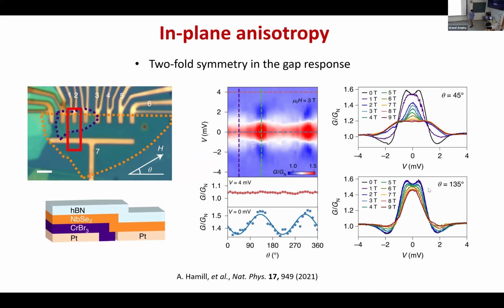Just note that in this particular study, they were tunneling through chromium bromide (CrBr3), which imposes its own order, and so there was an argument around that. So I don't think there's clear evidence that what you see here is completely originating from the niobium diselenide. It's sitting on a magnetic material. I also asked them, and they claim there was nothing special in the magnetic material. That's what they're saying. My humble opinion is about the magnetic rotation.